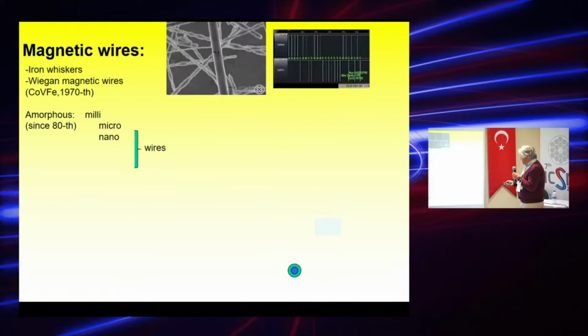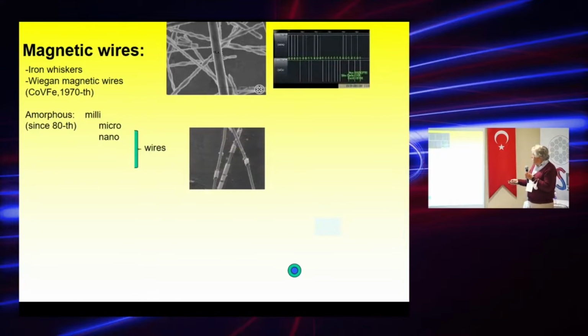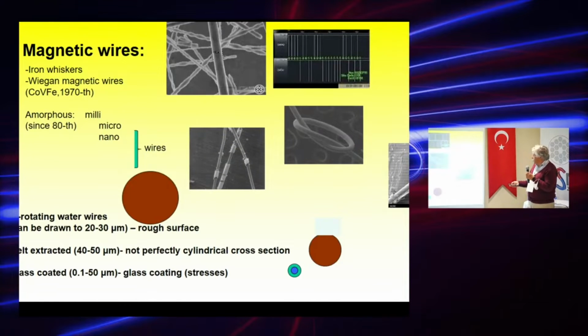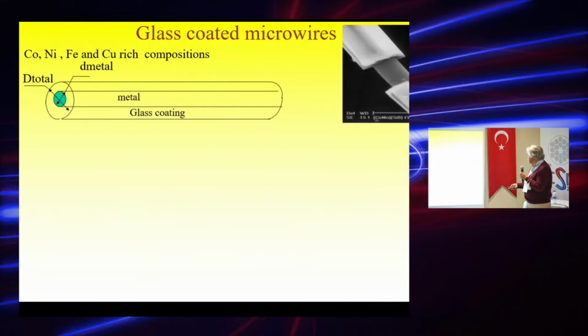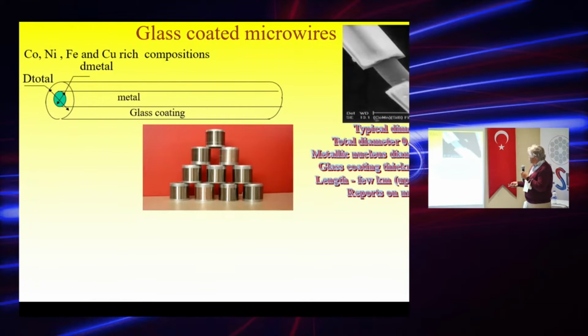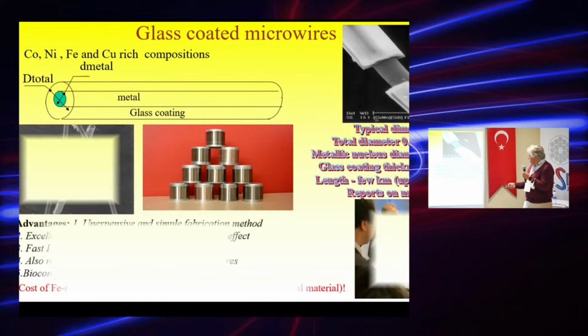In fact, we are working with magnetic wires. Magnetic wires have been known for many years, but we work with the family of so-called glass-coated microwires. These are the thinnest amorphous materials which can be produced by the rapid quenching technique. Previously, some crystalline materials were developed, and in our case, we have a perfectly cylindrical shape and diameters from sub-micrometric to a few micrometers. You can see the diameters here, and it can be produced almost in a continuous way. In one such bobbin, you can have a few kilometers of continuous microwires.